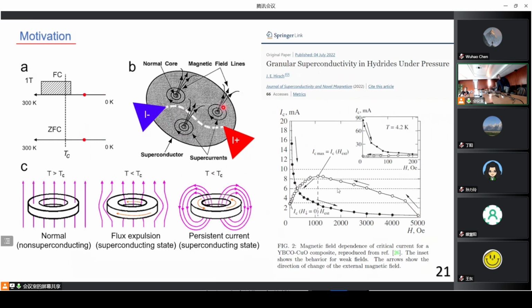So if there are trapped magnetic flux in the sample, it should change also the critical current which passes nearby these centers and close to the centers. So we should see a similar effect as Mikhail Eremets and Vasily Minkov saw in the SQUID measurements, but we also can see it in voltage-current measurements. If we measure the critical current, the trapped magnetic flux should affect the critical current and it should decrease.